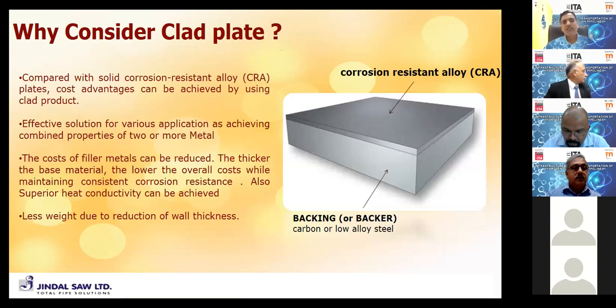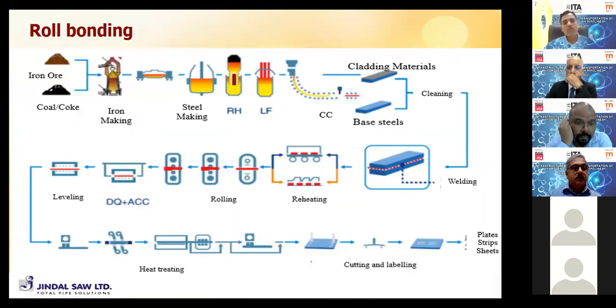So as I discussed, the plate can be used to form large diameter pipes. There is a backer, which can be carbon steel or low alloy steel, and the backing steel will be clad with the CRA, corrosion resistant alloy. Next, please. So I will discuss the roll bonding process. As we already heard about steel making, there will be 2 materials. One is the cladding material, another is the carbon steel base metal, which are joined and sealed together and then rolled. After rolling, it is split into 2 parts, and after cleaning and cutting, that can be used for pipe making. So this is one process which comes under the metallurgical bonded plates.